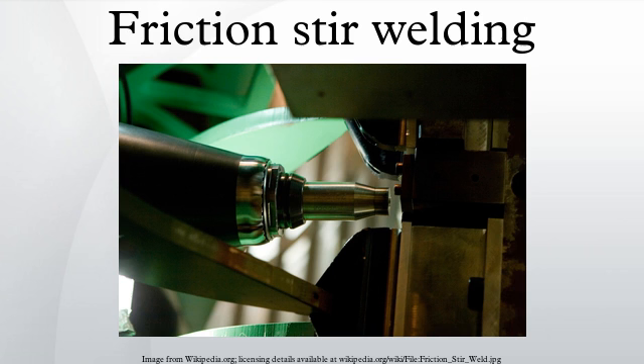This theory holds that some material does rotate around the pin, for at least one rotation, and it is this material movement that produces the onion ring structure in the stir zone. The researchers used a combination of thin copper strip inserts and a frozen pin technique, where the tool is rapidly stopped in place. They suggested that material motion occurs by two processes. Material on the advancing front side of a weld enters into a zone that rotates and advances with the pin. This material was very highly deformed and sloughs off behind the pin to form arc-shaped features when viewed from above.